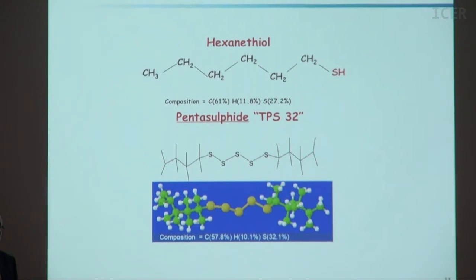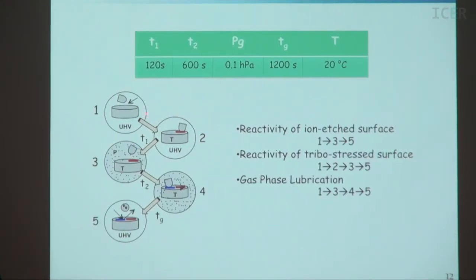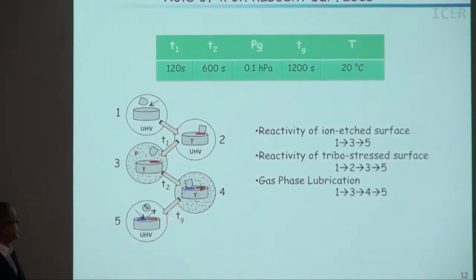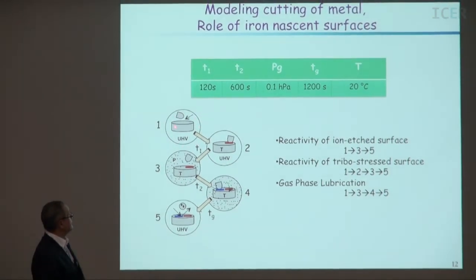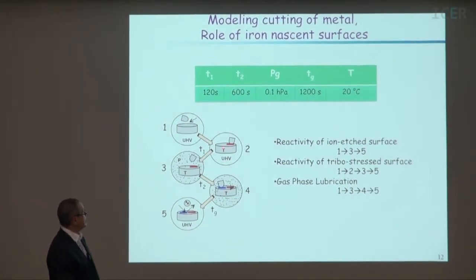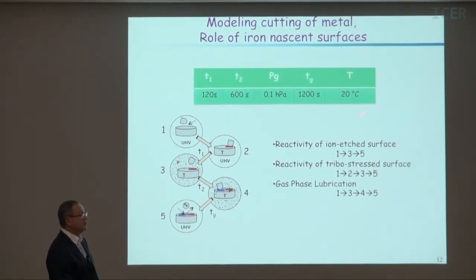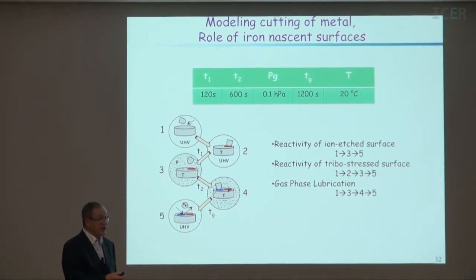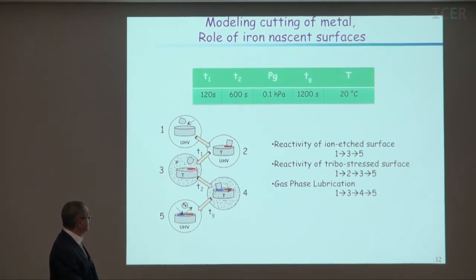So we would like to study the interaction of these molecules with the new surface formed after the cutting operation. So we used the strategy like I told you, first in vacuum. Here we remove the oxide because the nascent surface has no time to oxidize in the cutting operation. And after we make the friction in vacuum, expose to the gas, make the friction in the gas, and pump to analysis. This takes about 3 or 4 hours to make this whole operation.